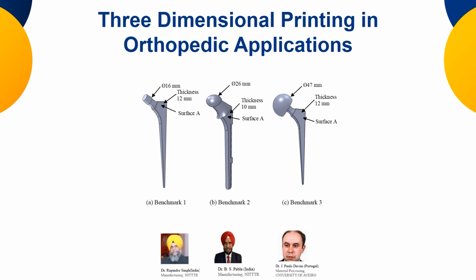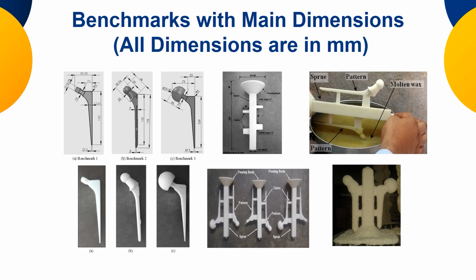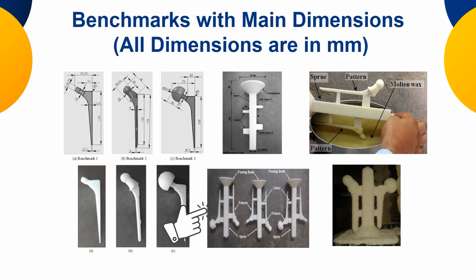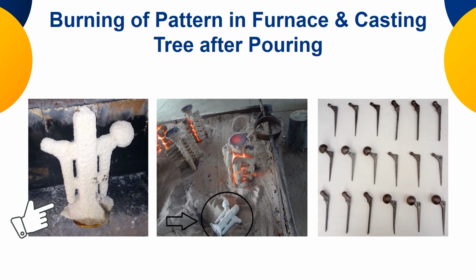Now this is the next case study that I want to show you, for the development of an orthopedic part. This is the typical hip joint, and for the hip replacement I am interested in developing some benchmarks, as you can see on this screen, of different dimensions along with the collaborator. Like in a typical casting study, we develop a pouring basin, then have a down sprue, then the runners and gates are there, right? Along with this, the different polymer parts that have been prepared by fused filament fabrication were attached to it. This is the sprue, here are the patterns attached, and then I am putting a molten wax coating around it to give it a smooth finish. Then the slurry coating around it, like a typical investment casting process, and then removal of the polymer part.